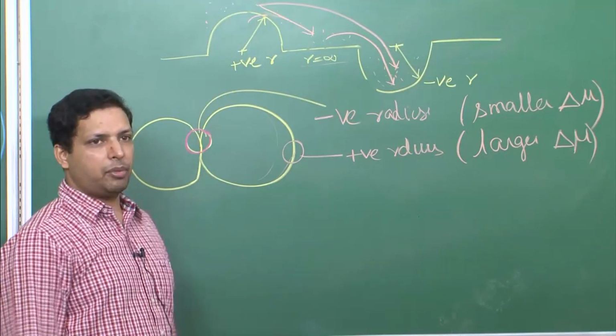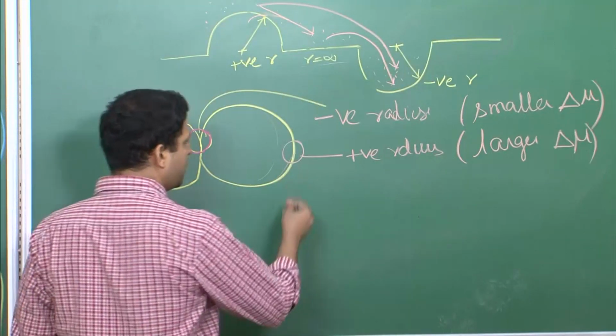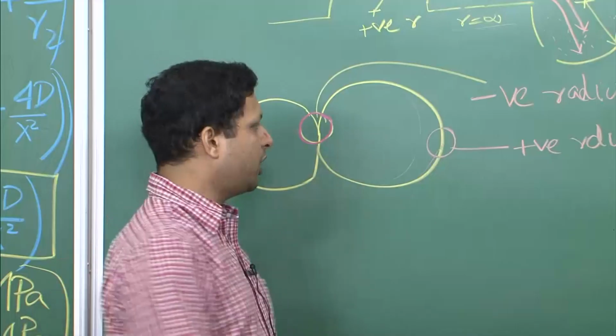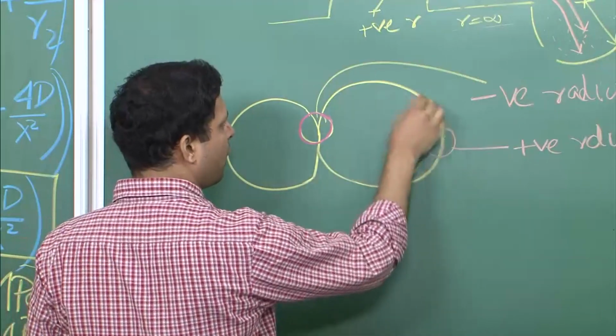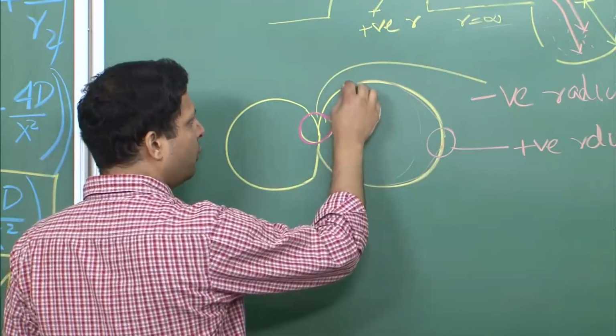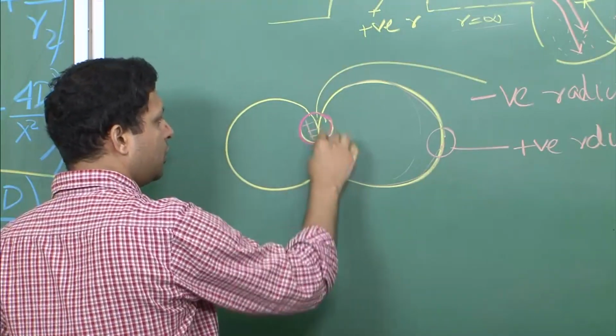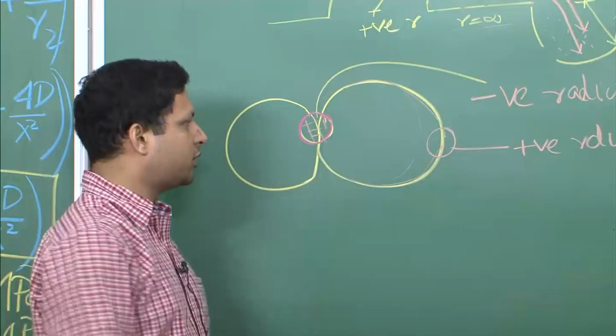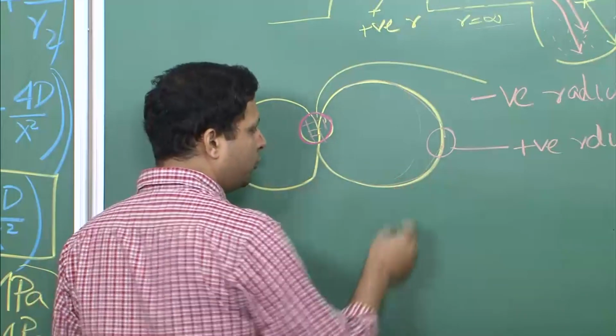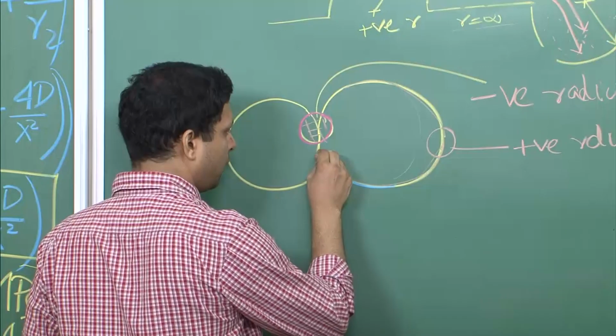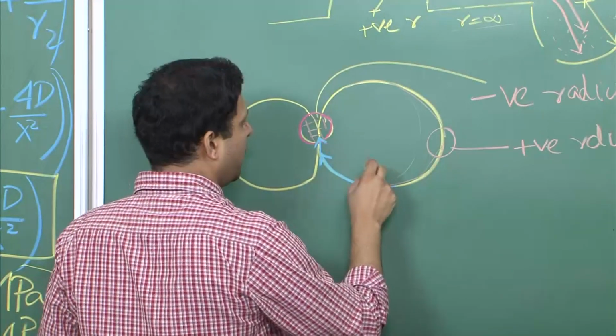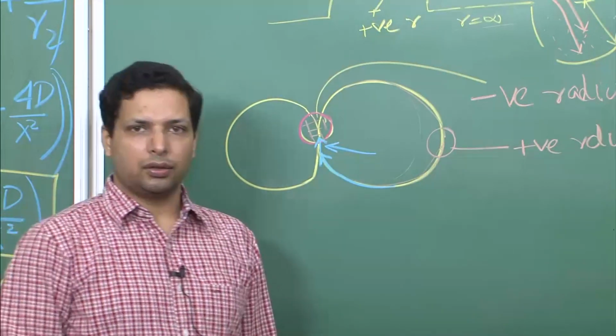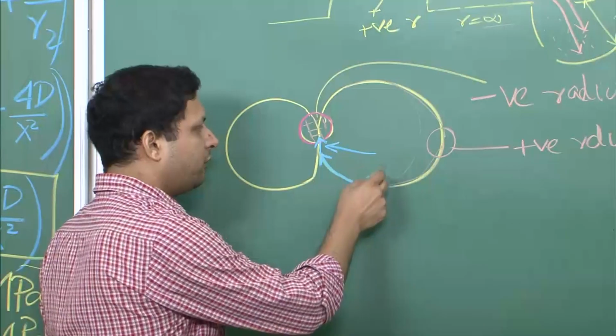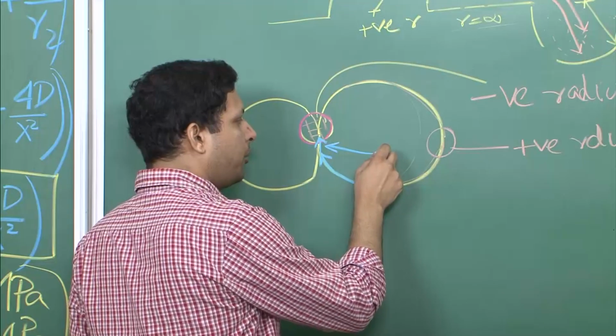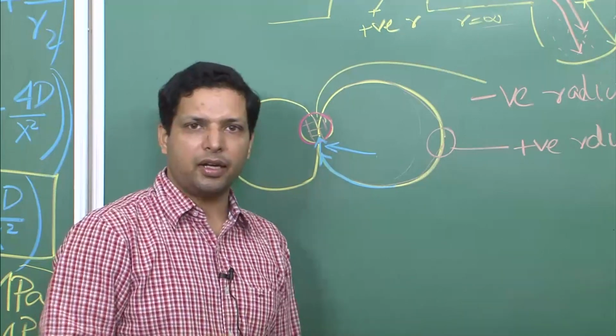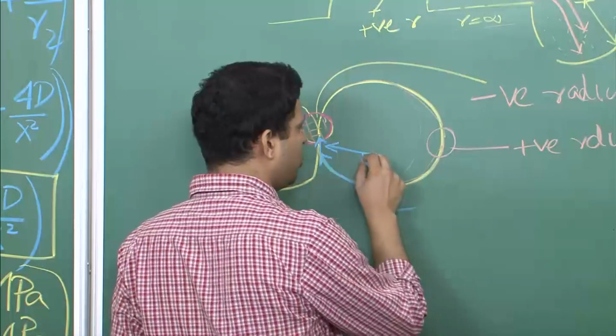So, from diffusion we know what will happen. From diffusion we know that material will have the tendency to flow, or to use the more appropriate word, to diffuse from this region, or all these regions where you have a higher chemical potential, into this region of lower chemical potential. And this diffusion can be of different types. It can move through the surface, it can move through the grain boundaries, it can move through the lattice. So, there are several kinds of diffusion that can take place, and the one where you have lattice diffusion taking place, particularly from the center or from the inside of the mass into the neck region, is the one that will contribute most to the densification.